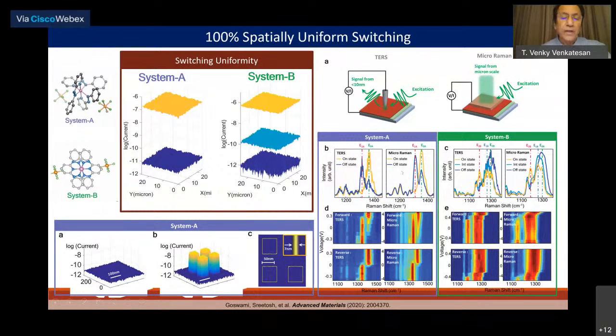The device is behaving exactly as one would expect. So this is, in a sense, very different from the oxide-based chemistry, where the primary mechanism is oxygen vacancy diffusion, and they end up forming essentially filaments. The filaments introduce a significant amount of plasticity in the circuit design, and they have to compensate for it. And we just don't have that problem with this particular electronic device.